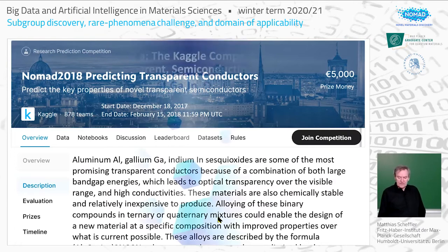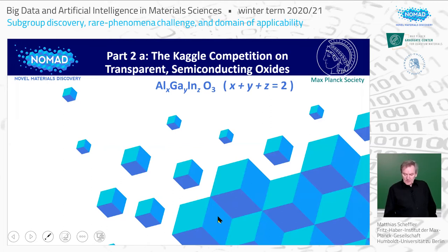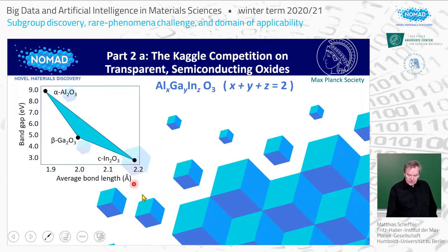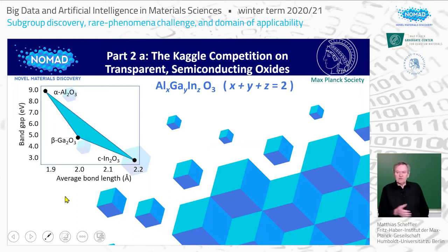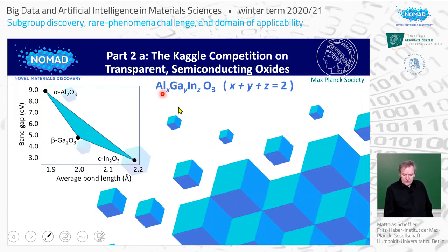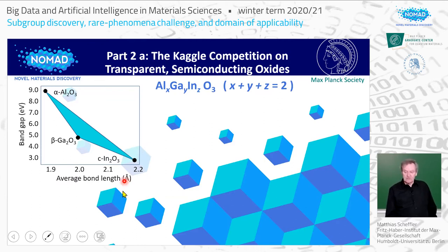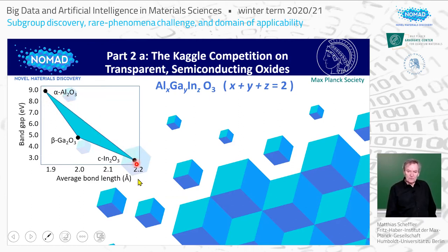We are talking about aluminum, gallium, and indium oxide, where the stoichiometry has two cations — X plus Y plus Z adding up to two — and oxygen three. The bandgap is plotted as a function of average bond length. Depending on X, Y, Z, the bond length between the cation and oxygen differs, so you can identify these systems by average bond length. The bandgap changes significantly — from close to 9 eV for alpha alumina down to about 3 eV for indium oxide.